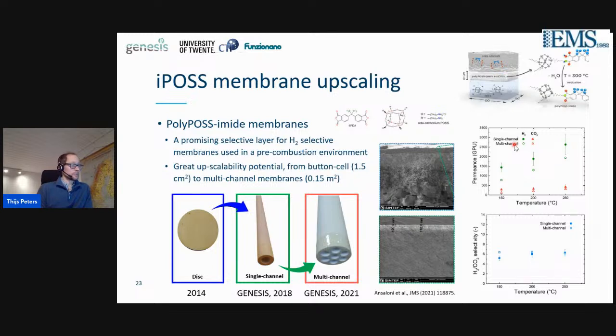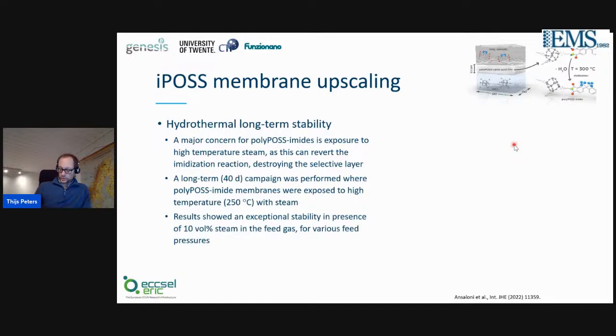Even the permeance of the tubular membranes was larger compared to the disc membranes because of the much lower support resistance that was obtained in the optimized tubular supports. Also in that project, we tested quite thoroughly the hydrothermal long-term stability, because the hydrothermal stability was a concern for those polyimide membranes, because at the typical temperature of operation, which is 200 to 250 degrees, in the presence of high temperature steam, the concern was that this could revert the imidization reaction, thereby destroying the selective layer.